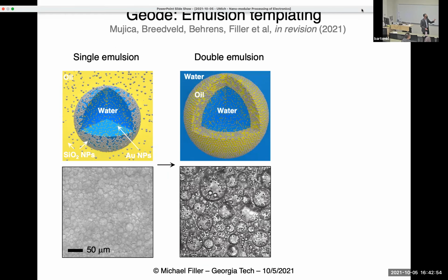Then you wrap that oil phase in another water continuous phase. That's called the second emulsion. And you can see what's starting to happen, right? The metal seed particles remain in the inner water phase. And now you're starting to coalesce these silica particles into something that looks like a shell of a capsule.